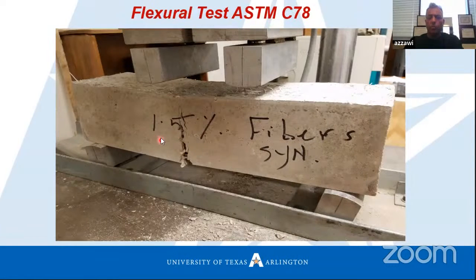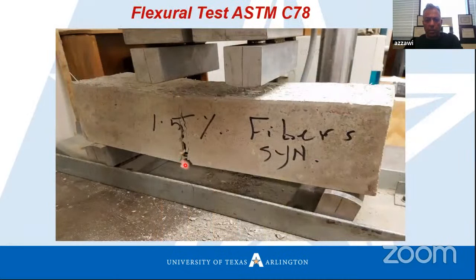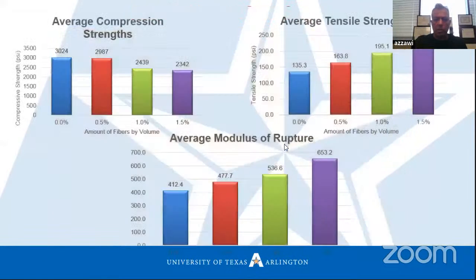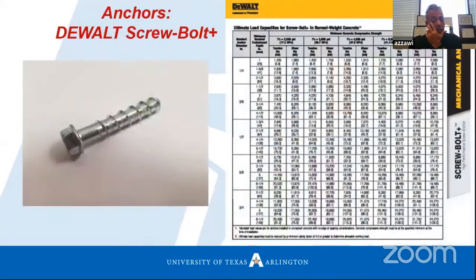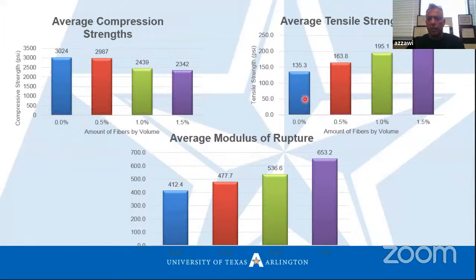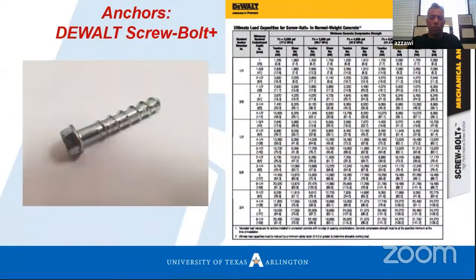This is one sample for 1.5% synthetic fiber, as we see. These are the synthetic fibers, not steel fibers. We have the results for compression, for tensile, for modulus of rupture. Yes, the synthetic fibers increase the tensile strength very well, and also the modulus of rupture, but they did not help that much to increase the compressive strength, which we don't worry too much about for concrete. What we need, in fact, is mainly to improve the tensile strength of concrete.